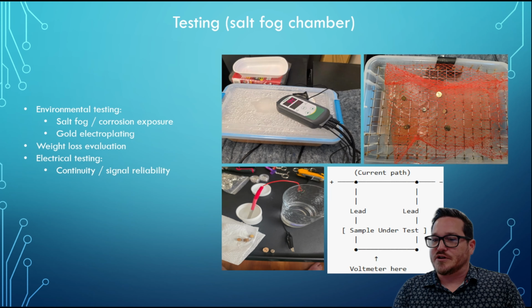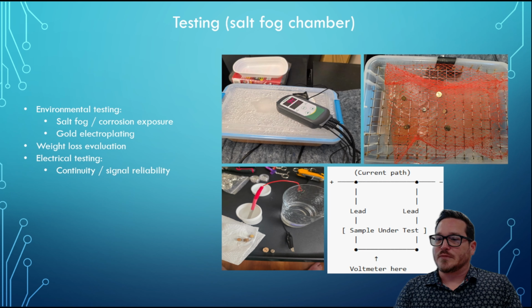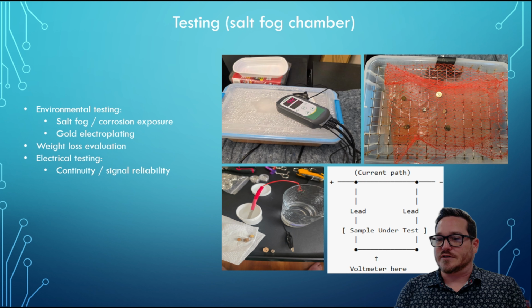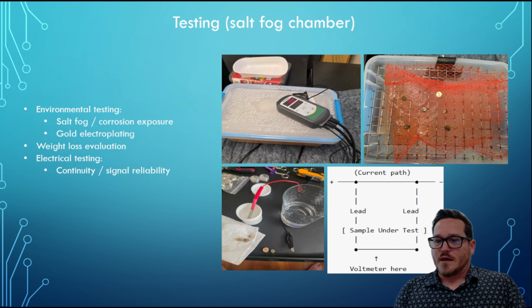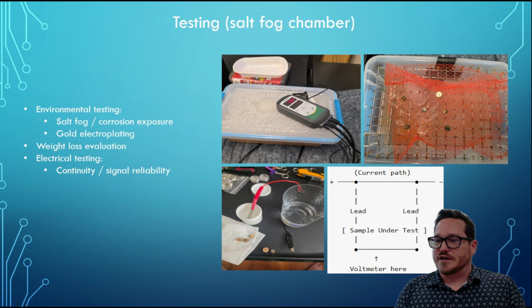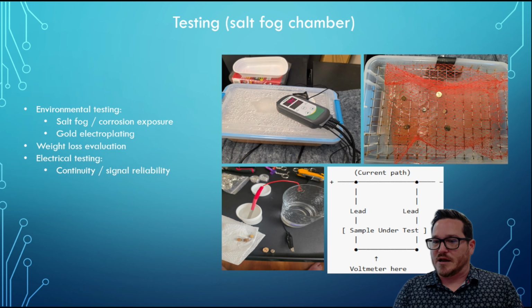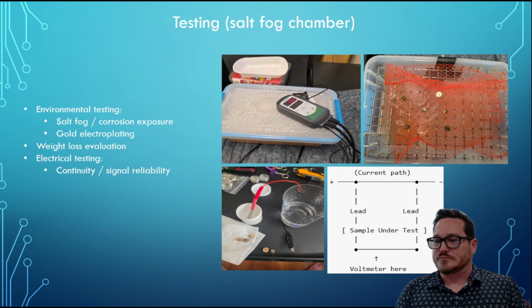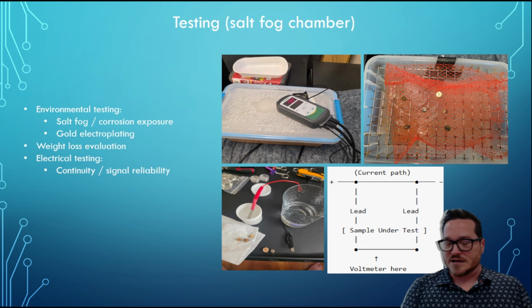As we know, gold is a good conductor and is supposed to be corrosion resistant, so I wanted to see if this will have an effect while in the salt fog chamber. After the saltwater exposure, I would visually inspect the samples, weigh them, and apply a current to them. By applying a constant current and using a multimeter to watch for voltage spikes, I could discern if there was increased resistance and in turn assume damage from corrosion. By weighing the samples, I would be able to see if the corrosion caused any degradation of the metal, resulting in a loss of mass.